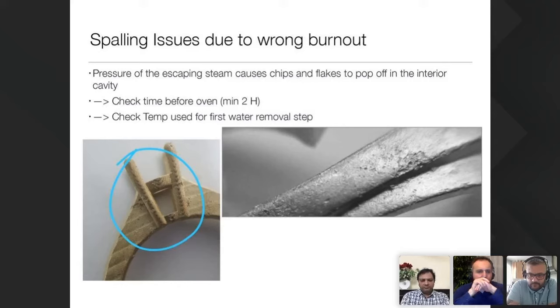Yeah, and that released part of the investment remains in the flask, and when you pour the metal, that gives you this negative offset on the surface, which is something you don't want. And we hate that because it's very difficult then to polish and to fix it. By the way, this happens now. People tend to say, this doesn't happen on wax, or it doesn't happen on that.